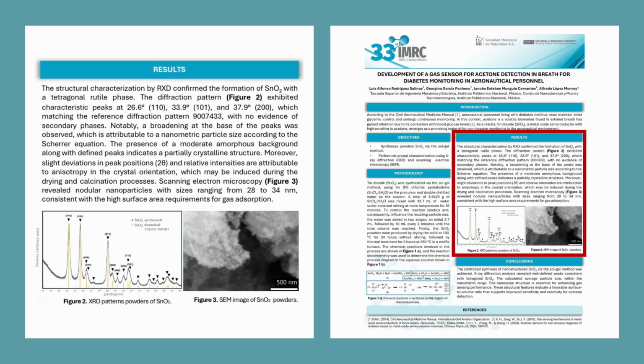The structural characterization via X-ray diffraction confirmed the successful formation of tin dioxide with a tetragonal rutile phase. As shown in Figure 2, the diffraction pattern exhibits characteristic peaks at 26 degrees, 33 degrees, and 37 degrees, matching perfectly with the reference data. Importantly, no evidence of secondary phases was observed. We also notice a broadening at the base of the peaks, which indicates a nanoparticle size.